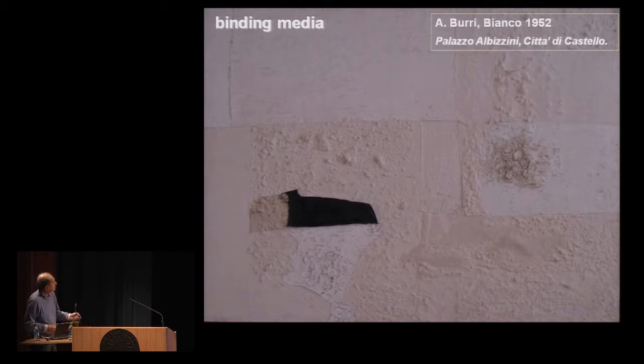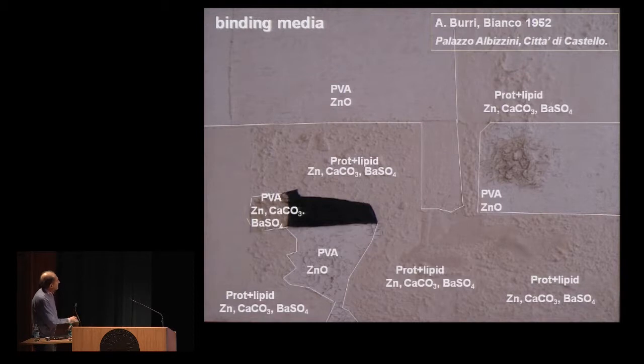But you can also detect the family of belonging of binders in contemporary paintings, like in this case, this painting by Alberto Burri, Bianco, that means white. It's a monochrome, and you can see that there are different areas that appear flat and others with some rugosity. We were able, carrying out several point measurements all over the surface of the painting, to characterize this area by the use of vinylic binder, polyvinyl acetate, together with zinc oxide as white pigment, also in this part, and also in this part, while in the other areas a proteic and lipidic binder was used together with zinc oxide, but also calcium carbonate and barium sulfate.